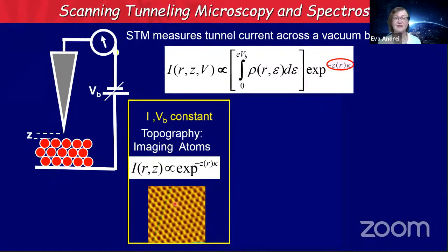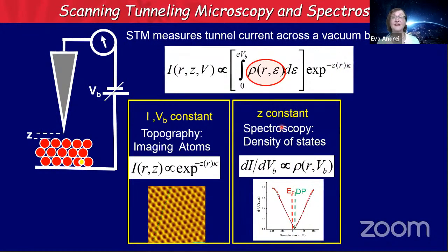In this particular example, this is the graphene lattice that we actually measured in our lab, and every corner here is a carbon atom. Another thing that you can measure with scanning tunneling microscopy is actually spectroscopy. You can extract the density of state here by taking the derivative of the current with respect to the bias, and that gives you direct access to the density of state. And then you vary the energy. You can measure the density of state as a function of energy.